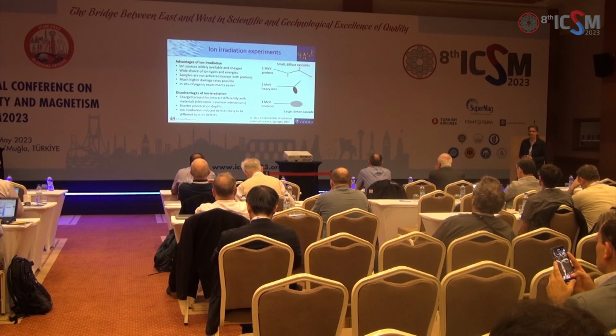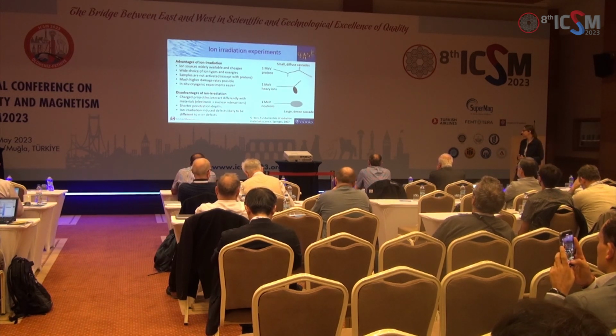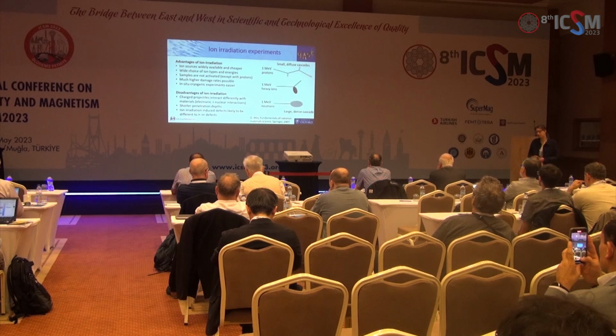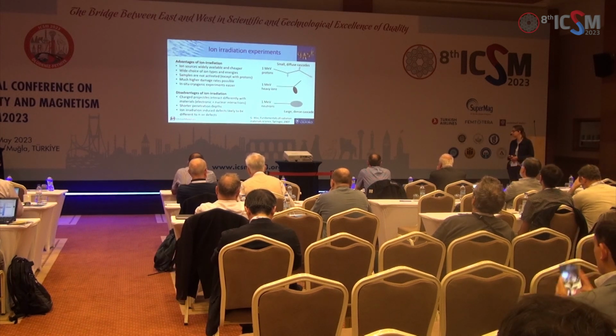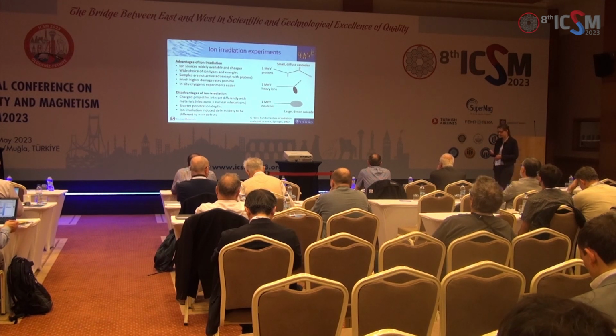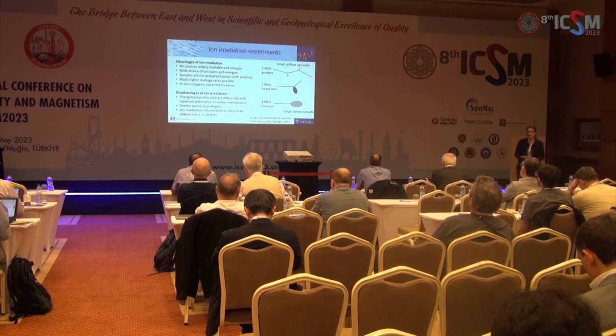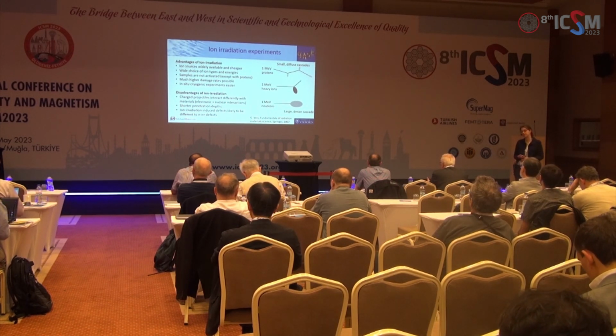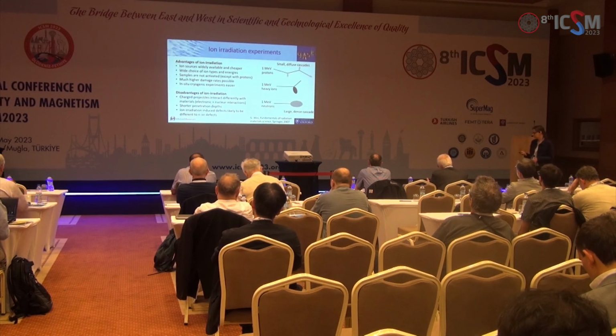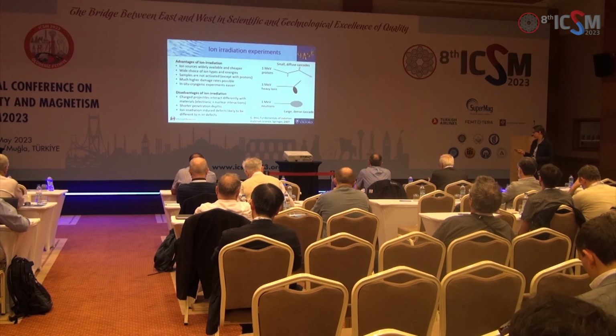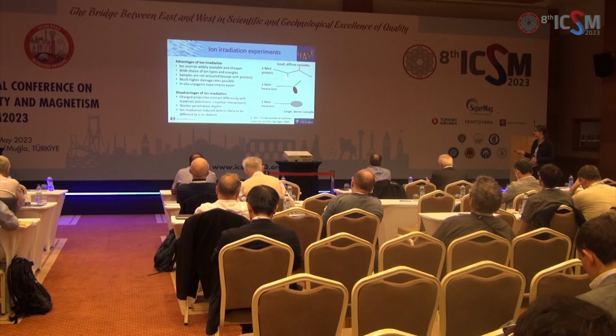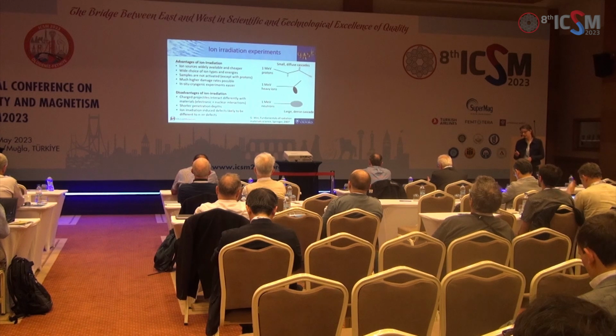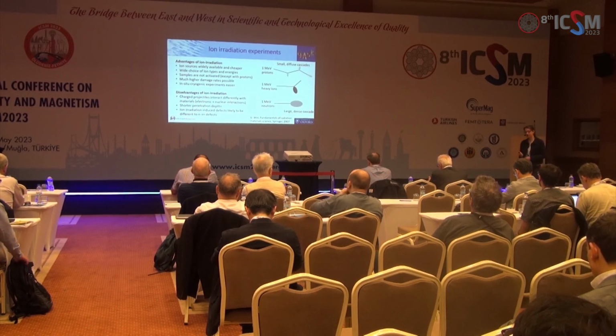Disadvantages, of course, are that they interact differently with materials. You've got both electronic and nuclear interactions, whereas with neutrons you just have nuclear interactions. They've got shorter penetration depths, which means we have to design our experiments a little bit differently. And we would expect that the defects they produce might be different to those that you get with neutrons. That's the question we've been trying to answer: how different are those defects? So a standard picture would say if we use light ions like protons or helium ions, you might get small diffuse cascades. Heavy ions may make bigger cascades that are a bit more like neutrons, but there are other issues with using heavy ions.